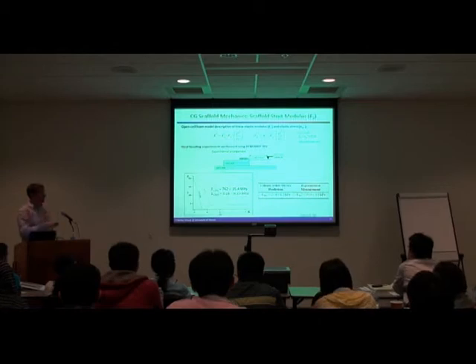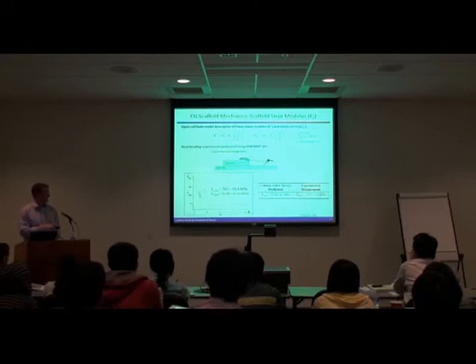All right, so one last step we wanted to get back to is to validate again this relationship I talked a little bit about, where you can relate the elastic modulus of your biomaterial to the elastic modulus of the material that it's made out of and the relative density squared. So that suggests that we should be able to perform mechanical tests on an individual fiber from the scaffold and mechanical tests on the entire scaffold itself and relate them together. And we've done some work there where we've done macroscopic compression and tension tests, then cut out individual fibers and done AFM tests on them to do bending tests. And we've related quite well to find the elastic modulus of the dry and hydrated fibers on their own. They're up in the megapascal ranges, and we see a nice correlation between our measured elastic modulus of the fiber, our predicted modulus of the entire scaffold, about 27 kilopascals, and the modulus of the scaffold, this one variant I'm describing, was actually 30 kilopascals. So we're seeing really good correlation between modeling predictions and experimental results.